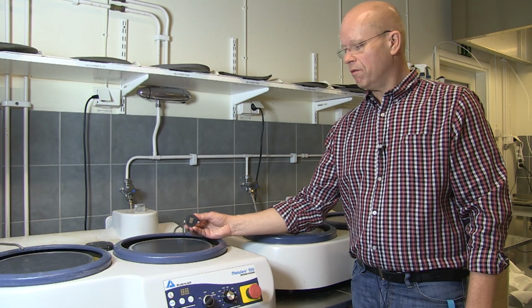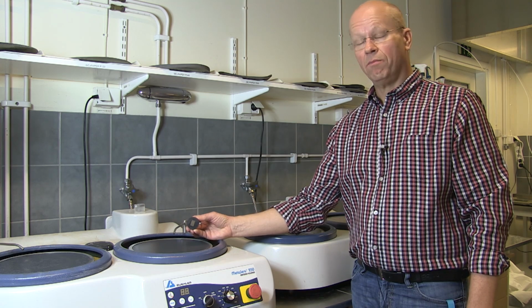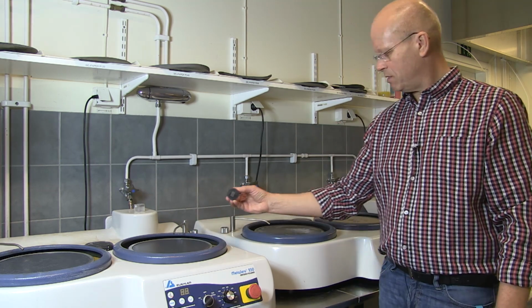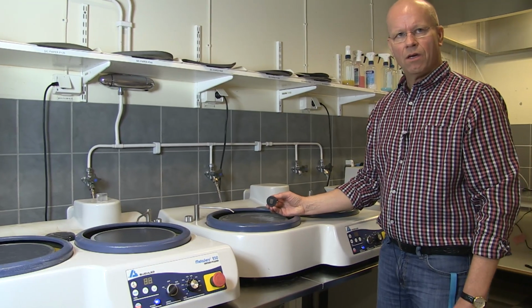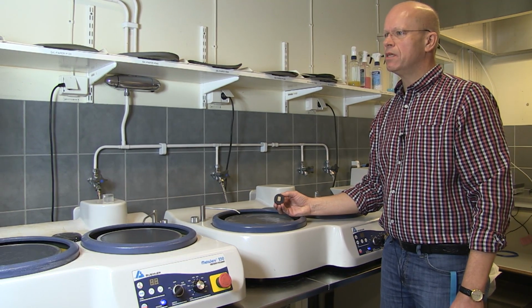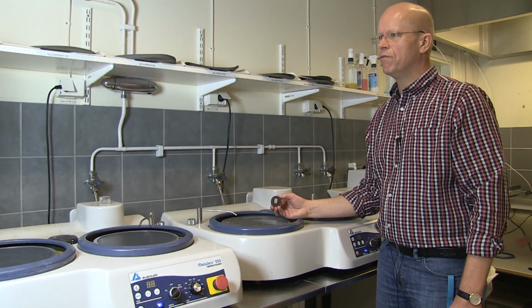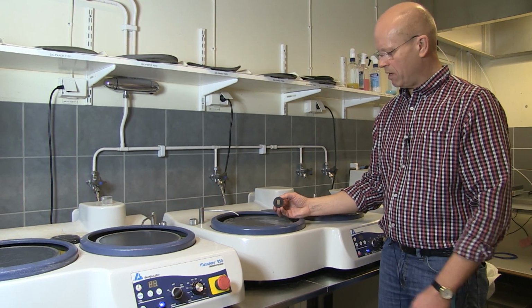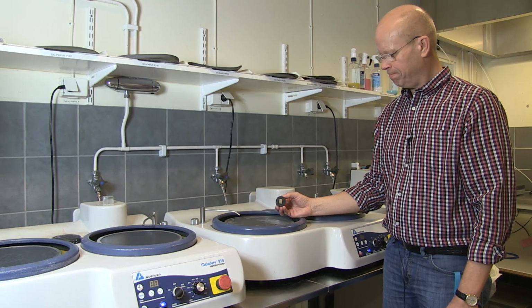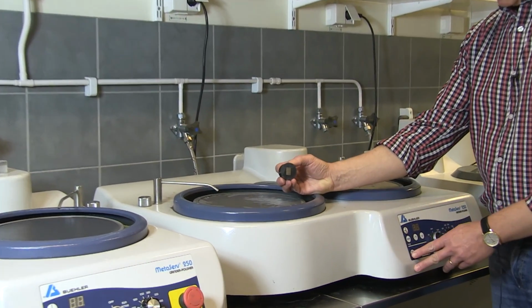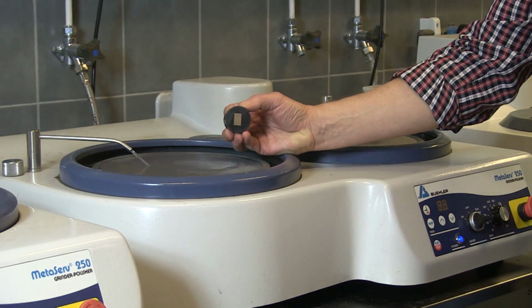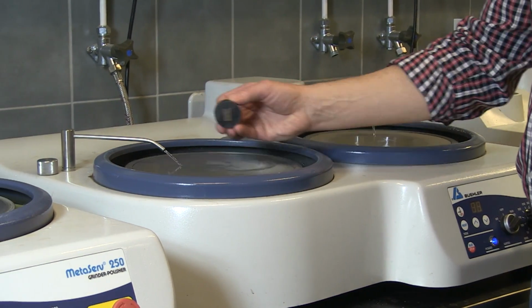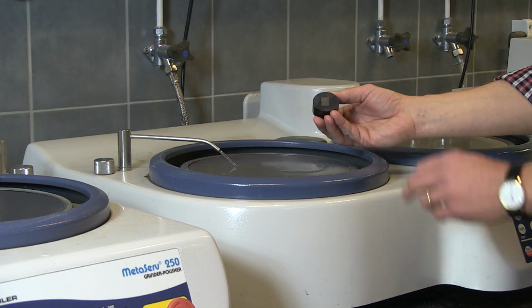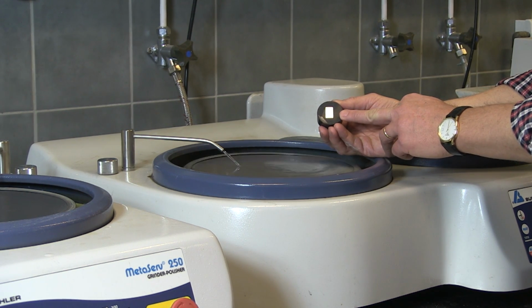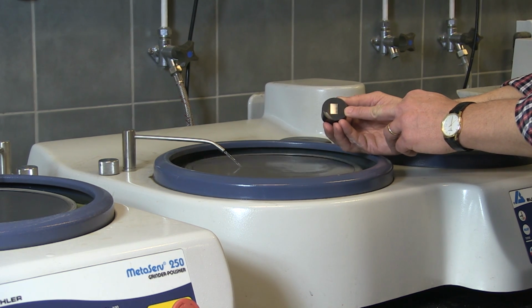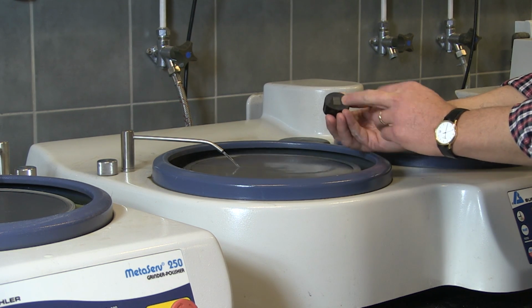So now I will move on from the first step on P240 paper to the next step, which is here on this machine, on P600 paper. And P600, it's 25 micrometers. So I'm moving from 60 micrometer to 25 micrometer silicon carbide particles here. I turn the machine on, same as on the other machine. Water is running, and I have already prepared it with a P600 paper here. From last step, I rotate the sample 90 degrees, so I get the scratches coming in perpendicular again, you remember?